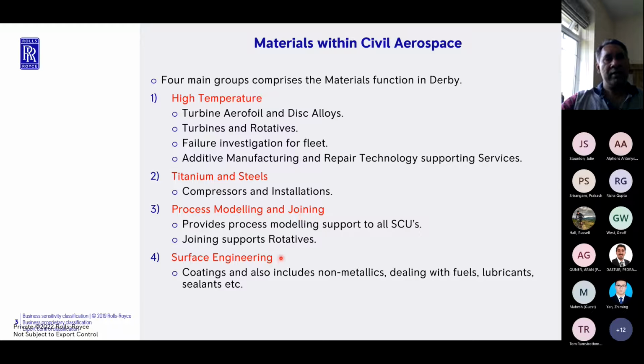And then there's a surface engineering group. This is again a very important group because practically every single turbine component is coated. You never ever have an uncoated turbine component, simply because at those kind of operating temperatures, you would see corrosion and you would see oxidation. So you need to provide some kind of protective coating to the blade or the vane or the segment. So you've got a surface engineering group that deals a lot with coatings and bond coats. So basically TBCs, bond coats.